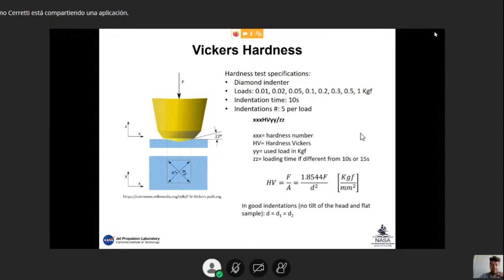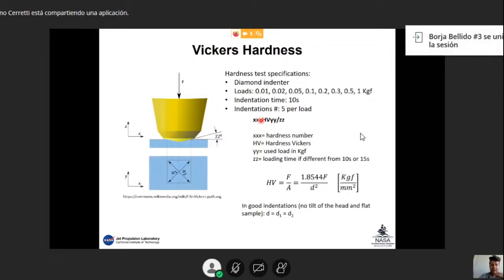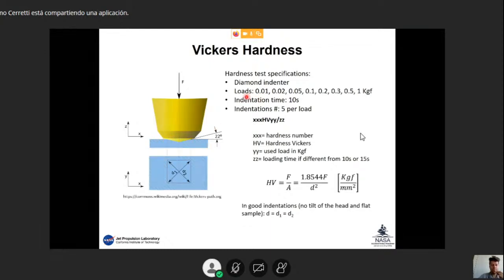You're probably familiar with these techniques, but I still repeat the general theory behind. So we have a diamond indenter. This indenter is brought into contact with the surface, and then a pressure is applied. We investigated loads going from 10 grams to 1 kilogram force. The indentation time was 10 seconds, so we applied this force for 10 seconds, and we did 5 indentations per each load, and then we took the average value.